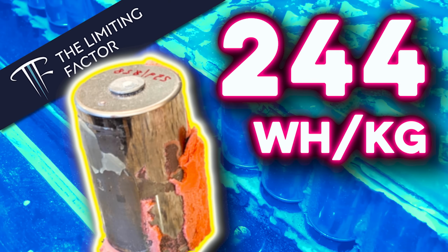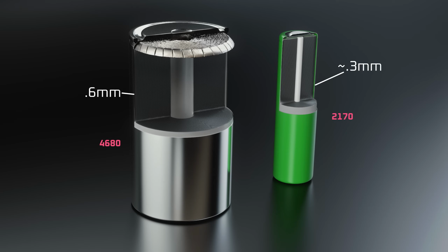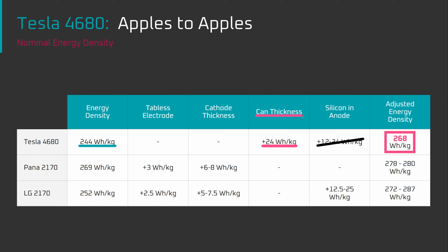To kick things off, 2 years ago when I released the results from the testing from the Generation 1 4680 cell, I showed that the thickness of the cell can was roughly double the thickness of a 2170 cell can. By my back-of-the-napkin math, I estimated that reducing the thickness of the 4680 cell can from about 0.6 millimeters to 0.3 millimeters to match the 2170 cell would increase its energy density by up to 24 watt-hours per kilogram.